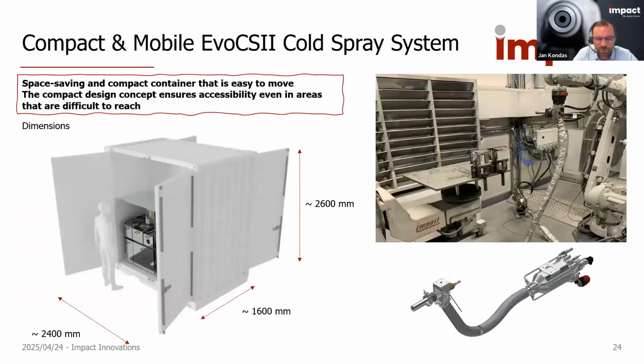Last but not least, I would like also to mention the possibility of a compact delivery of a cold spray system for in situ cold spray repairs, where we are utilizing also in combination with the so-called portable adapter, which is a remote nozzle connected to the cold spray gun, as you can see on the top image, which has a much higher flexibility, lower weight, better accessibility compared to our standard gun types. This setup we are widely using for aluminum repair application development, and with this we have also deposited all the materials, showing as-sprayed ductility and bulk-like properties in case of aluminum using nitrogen as process gas.